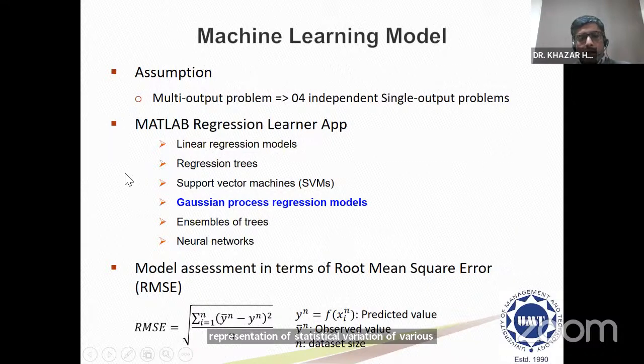In the machine learning field, there are several methods to train the model. For example, the MATLAB regression app provides these 6 methods. We used the first 5. Neural networks were available, but we haven't used them. And we measured the accuracy or assessment of the model in terms of root mean square error. And we found out that the Gaussian process regression model is the most effective in our problem.